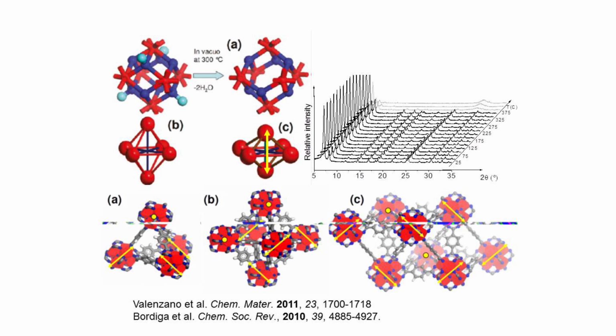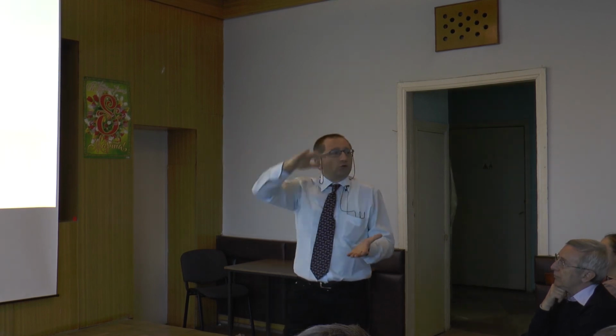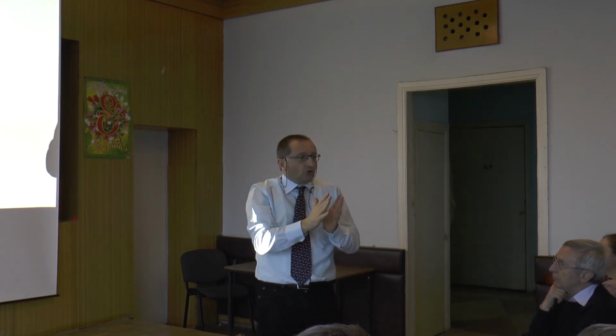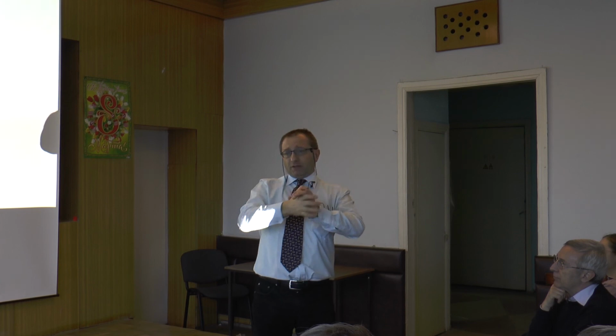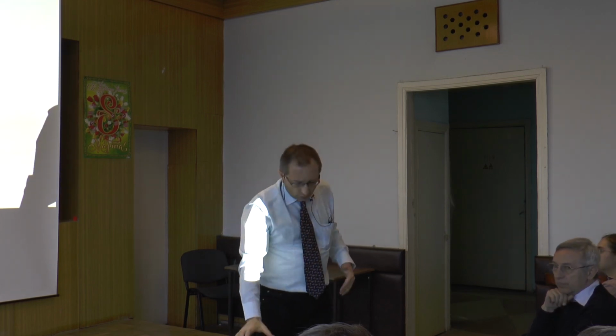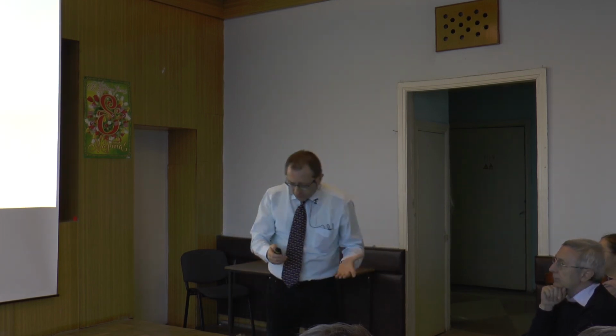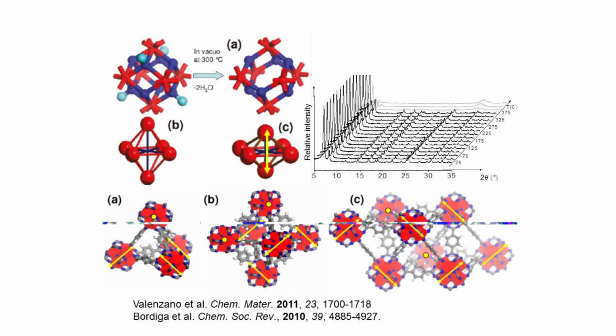So this must have been seen by X-ray diffraction. Why can we not see this by X-ray diffraction? In X-ray diffraction this would lead to a reduction of the symmetry, so you should see the appearance of new low symmetry peaks. But we don't see anything. There are no peaks there. Why? Well, because this contraction is random.